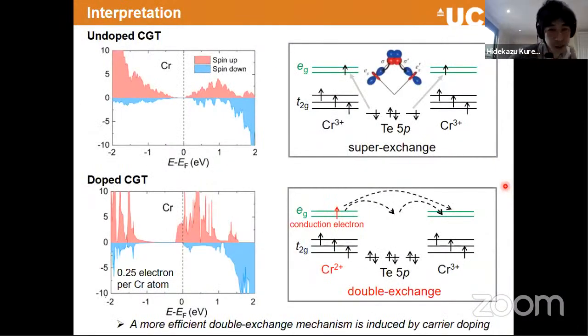Right, so just go back to the interpretation, because I sketched out the driving magnetism of this system at the beginning. In the undoped case, as I already explained, the driving mechanism is basically the excited states of this one electron spin into the EG state. By doing that, we can get the energy gain of the Hund's energy, and that can reduce the total free energy as a driving mechanism of the ferromagnetism.